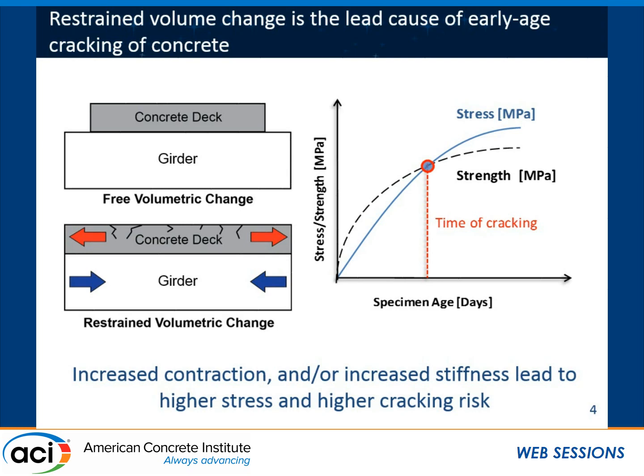First thing is that it's been found and confirmed repeatedly that the primary cause of early age cracking is restrained volume change, as opposed to things like traffic loads and other types of mechanical loads. So essentially what we have, and our previous speaker also referred to this, is a concrete deck that is cast in place over a girder, and the concrete naturally would like to shrink or contract after it's been cast. This could be a thermal contraction after the concrete temperature peaks around time of setting and then cools down to the ambient, and it also could be because of drying shrinkage or autogenous shrinkage. However, the girder doesn't want to shrink, and as a result of this, we cause this restraint effect, tensile stress, and cracking in the concrete deck.